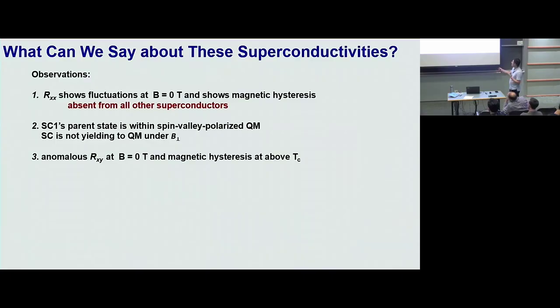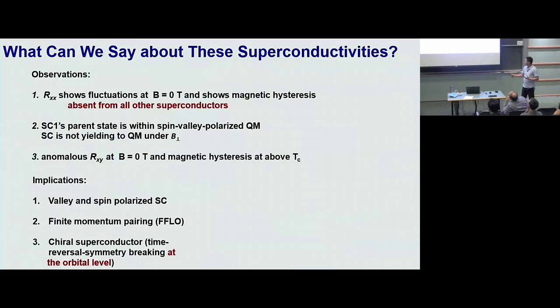And number 3 is above TC, you have anomalous Hall, magnetic hysteresis. And this implies that, okay, the superconductor has to be a valley and spin polarized superconductor. Because it's valley polarized, the Cooper pair must have finite momentum, like in FFLO. And it is a chiral superconductor because time reversal symmetry is broken. And it's broken at the orbital level. Okay, so it's not like broken by the spin, and the orbital can be a simple P wave, which is not time reversal symmetry breaking. This is broken at the orbital level, so it is a chiral superconductor.